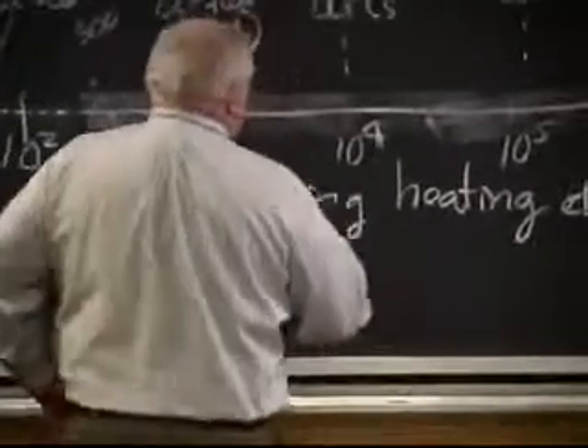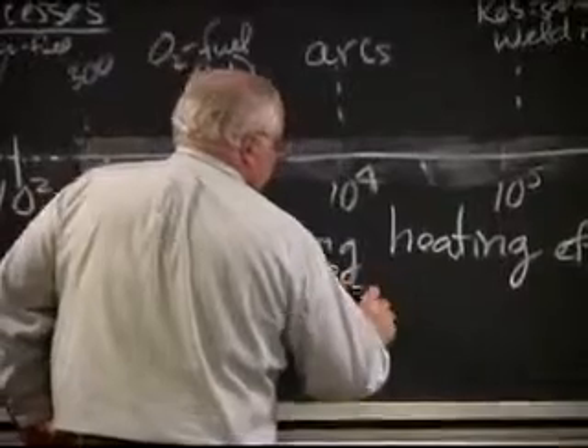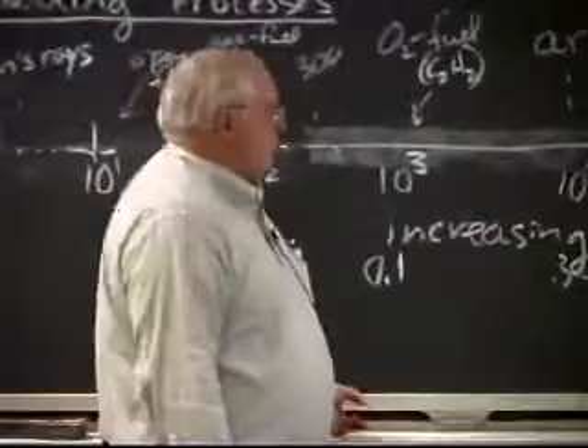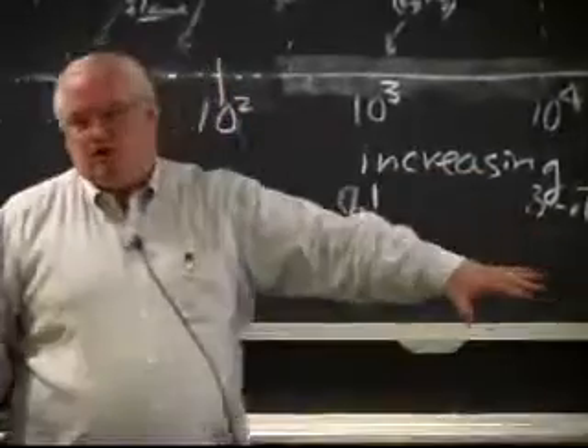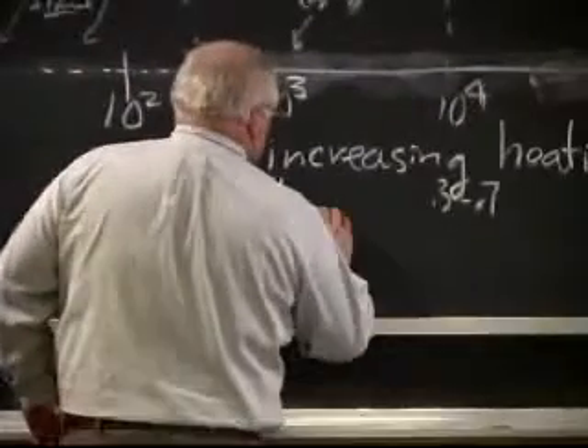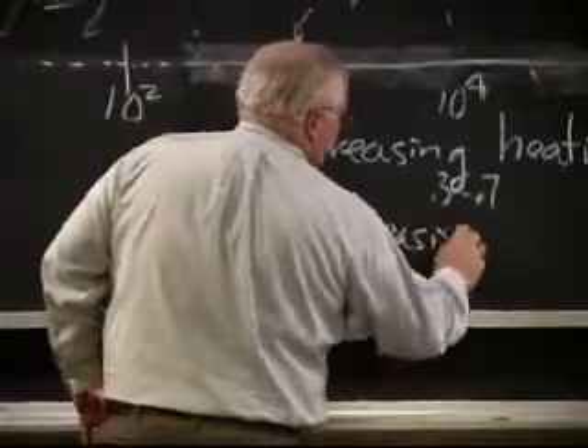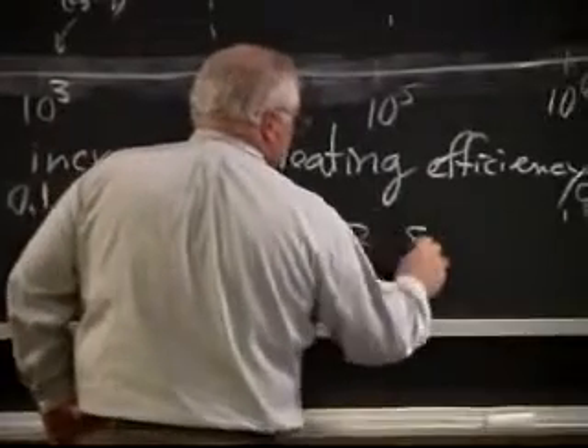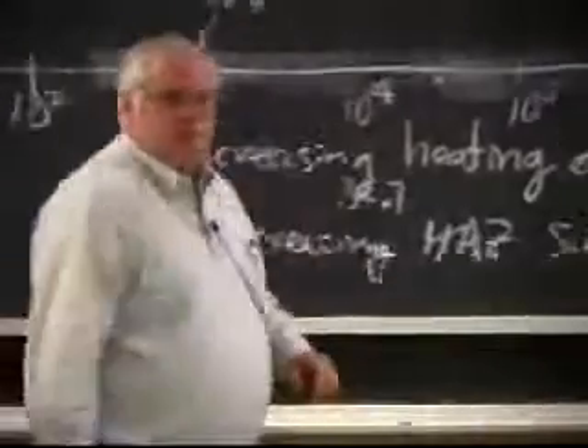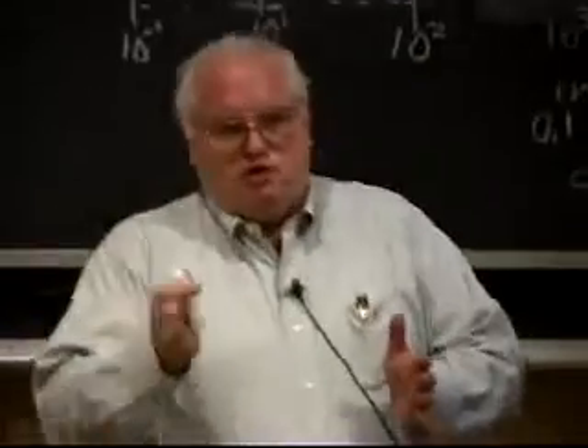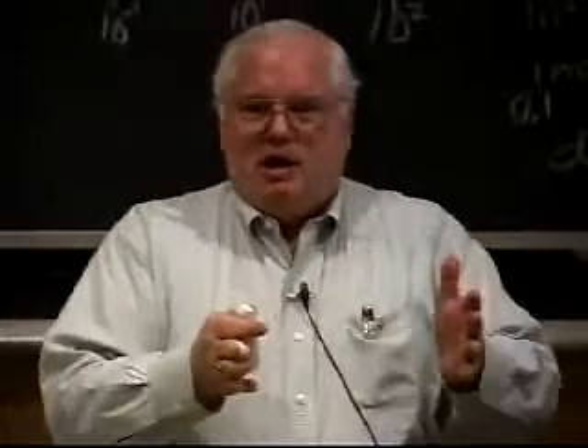And in here, in arcs, it can be anywhere from 0.3 to 0.7, typical numbers in the literature, depending on the type of arc. Now, if I have increasing heating efficiency, I also have decreasing heat affected zone size, right? The heat affected zone is the region between the fusion line where I melted into the solid for some distance where I've altered the structure of the metal. In a steel, that's typically the gamma-alpha transformation where you go from FCC to BCC crystal structure. So you actually have a very distinct heat affected zone.